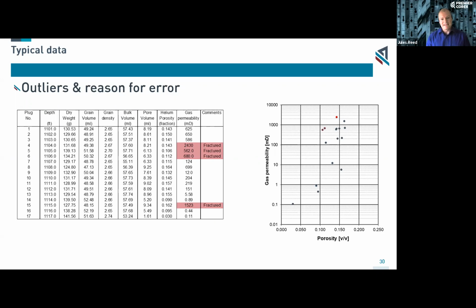variables, other metadata, and that is that 4 of these samples were fractured. Now, most laboratories would inform you of this, and they may not even report the fractured permeability. But those fractured permeability are those highest ones there on the plot. And we can begin to say, well, we don't believe these data because they're from fractured core. What we're measuring is the fracture, not the matrix.